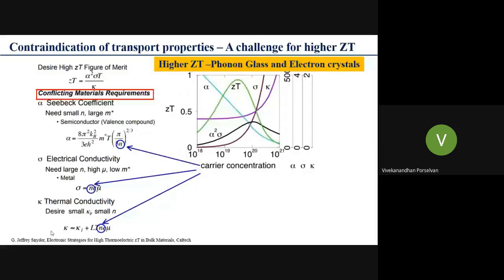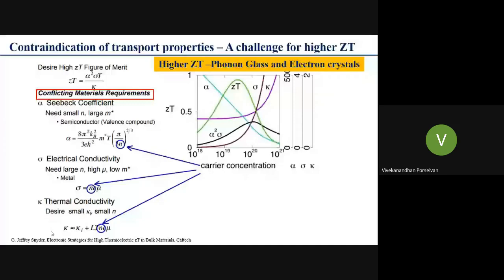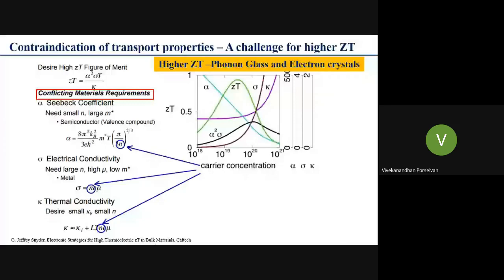It seems a thermoelectric material should have the characteristics of a phonon glass, which has very, very low thermal conductivity, and an electron crystal, which has very, very high electrical conductivity. So we should have one single material that behaves with high electrical conductivity like metals, and low thermal conductivity like wood. To achieve a higher ZT, we should tailor a material to behave like a phonon glass and electron crystal. So there comes the challenge of trading off between electrical conductivity and thermal conductivity to achieve the optimum ZT.